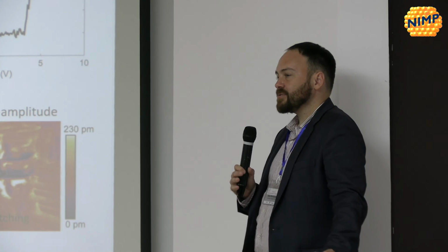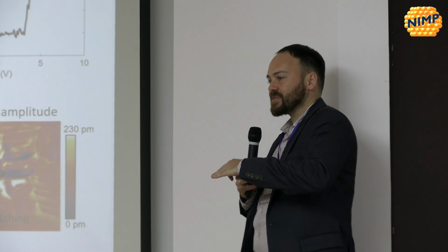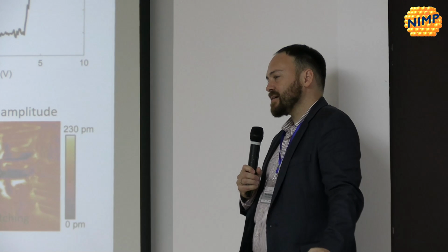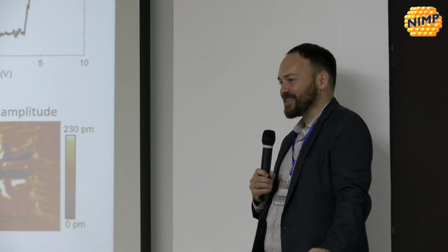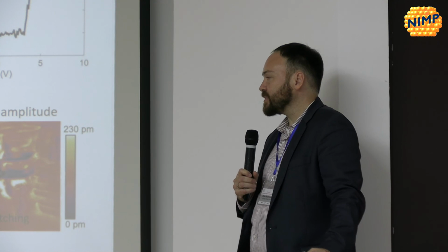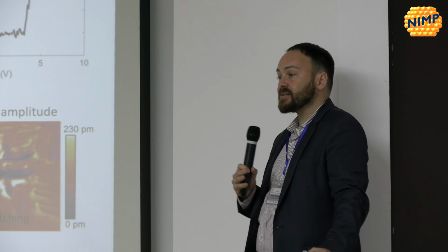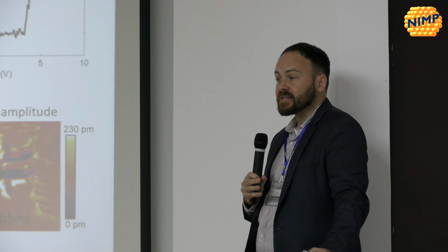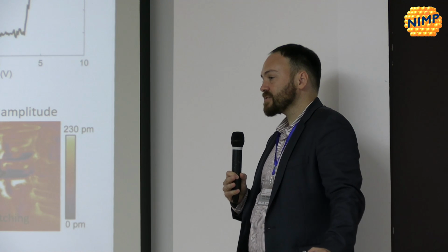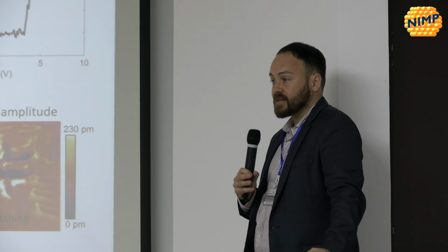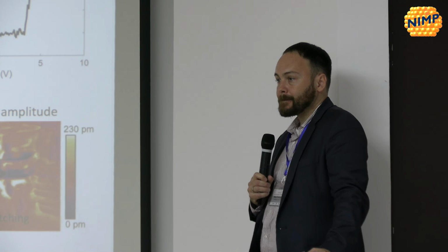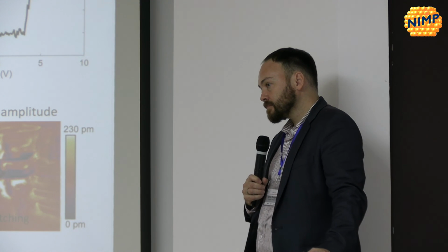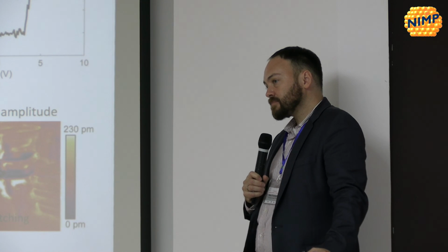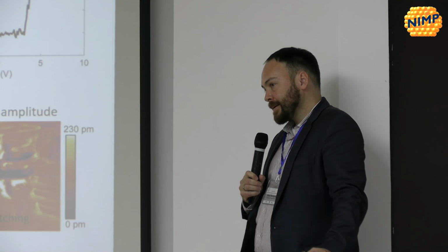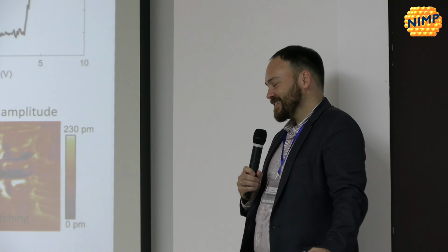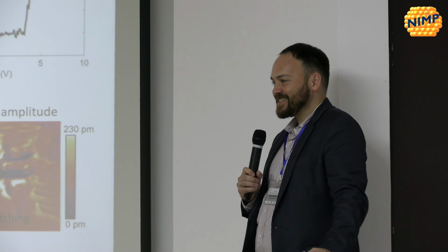It's similar to the idea that the barrier is being reduced between the ferroelectric states. I wasn't sure how to probe it exactly in our experiment. But I think we don't rule that out. It could just be becoming more conductive because it's easier to switch in both directions, and it'd be interesting to see if the same trend is observed in other materials that might not be as conductive. Okay. But does the fact that bismuth ferrite is multiferroic influence this finding somehow? Is there any difference if you do it on a normal ferroelectric with respect to bismuth ferrite? Yeah, there's some magnetostriction.